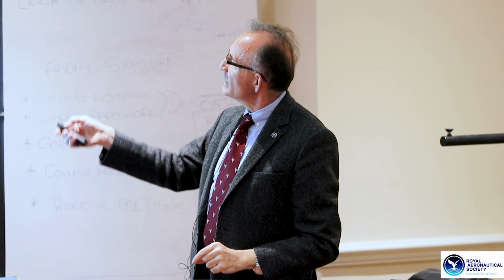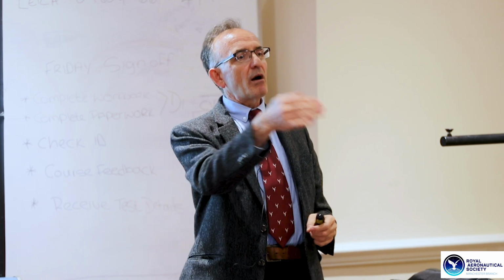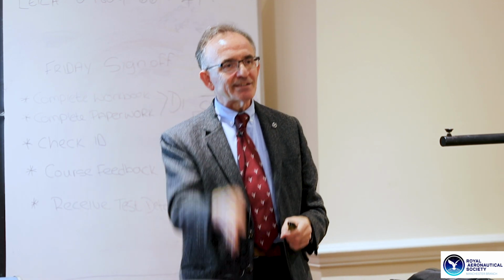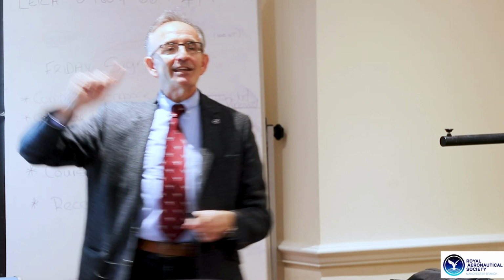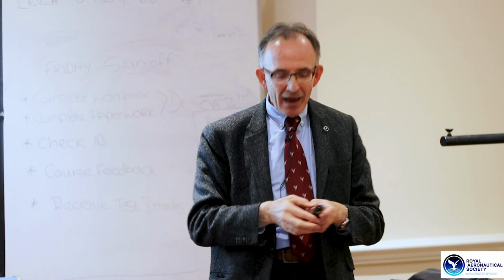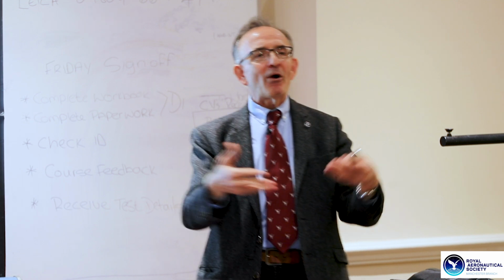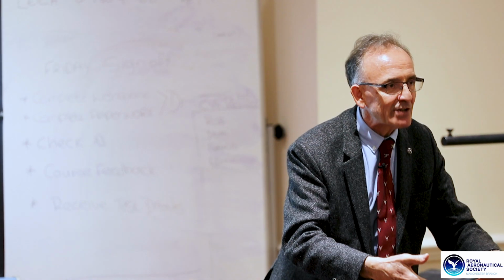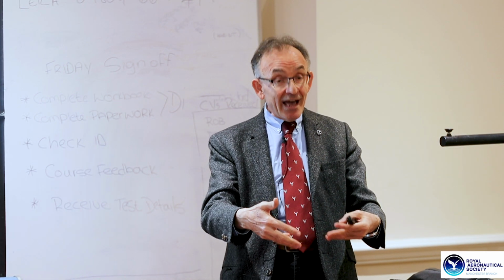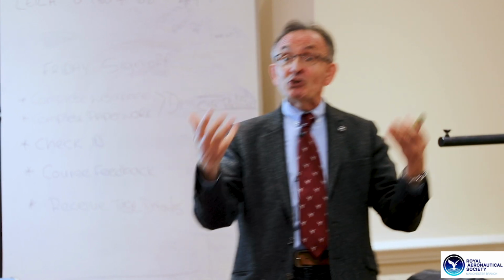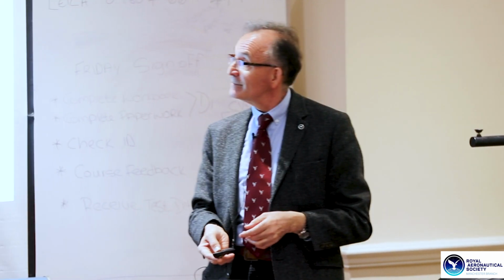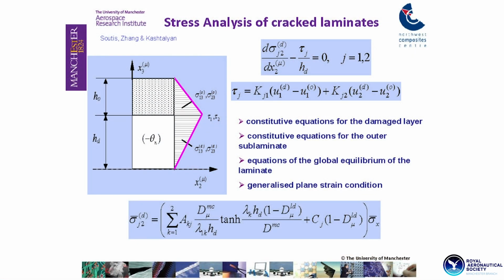And then if we load it in the transverse direction as well, in addition to 90-degree cracks, we also get splits along the zero plies, which again create local delaminations at the tip of that crack. And then of course those delaminations, when they grow, will allow the environment to penetrate into our structure. They will allow moisture to get into our composite. Moisture will plasticize the resin, and it will reduce the load carrying capability of the composite. And this is where I spend my time developing mathematical models that can tell us by how much the strength or the stiffness or the long-term performance of the composite will be affected by the matrix cracking, the delamination, the splitting, taking into account the environment that the composite operates in.